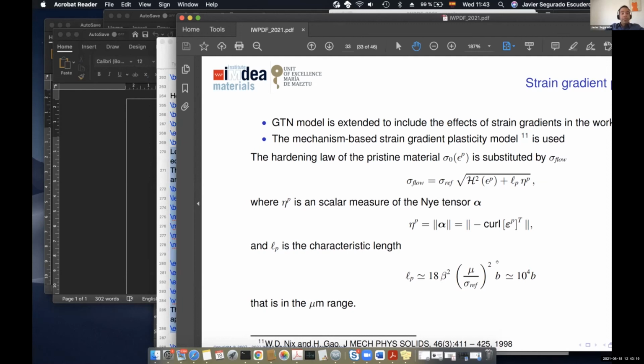This is one thing. The other one is the damage characteristic length, the size of the band. This is even worse, because in this case, it has been shown that this characteristic length is not even material dependent, because you can find different band thickness for the same material under different loading conditions, for different triaxialities. So it's convenient to introduce this characteristic length, but it's not like the yield stress or other parameters that are well defined and related to a material. They are controversial parameters that, from an engineering viewpoint, can only be obtained by standard physical principles in an order of magnitude. And to be accurate, somehow you have to make tests and obtain them for the particular condition you want to study.